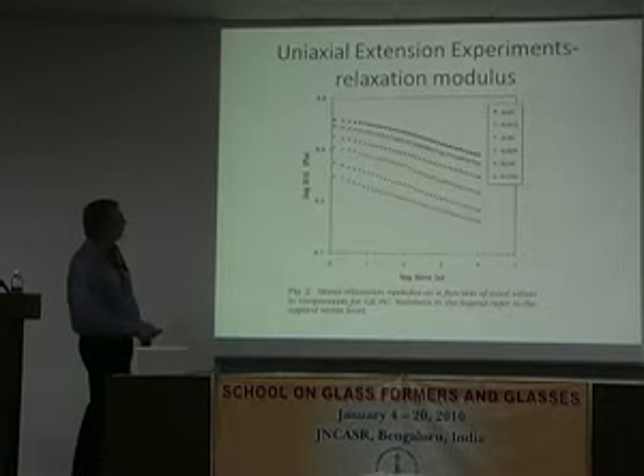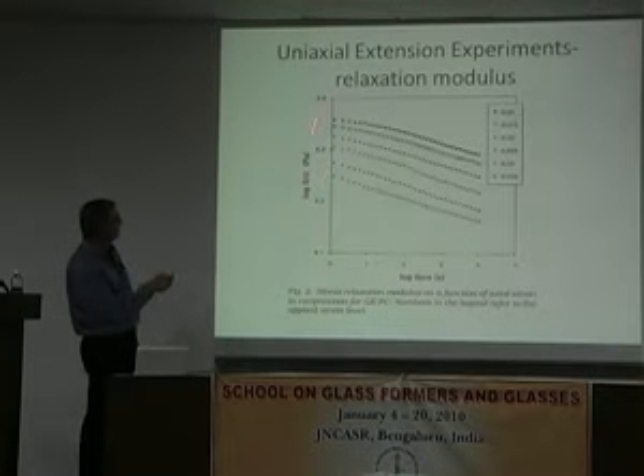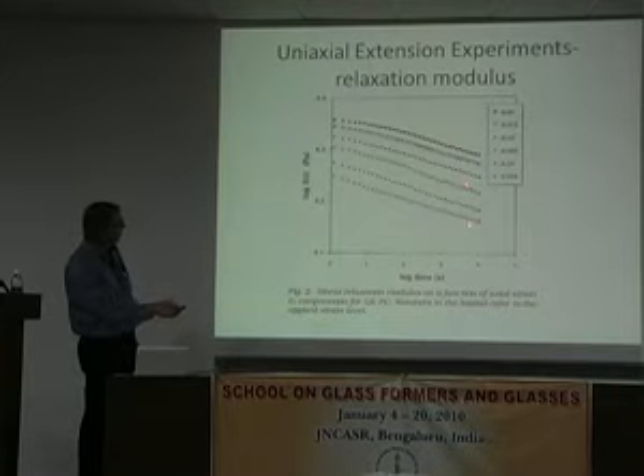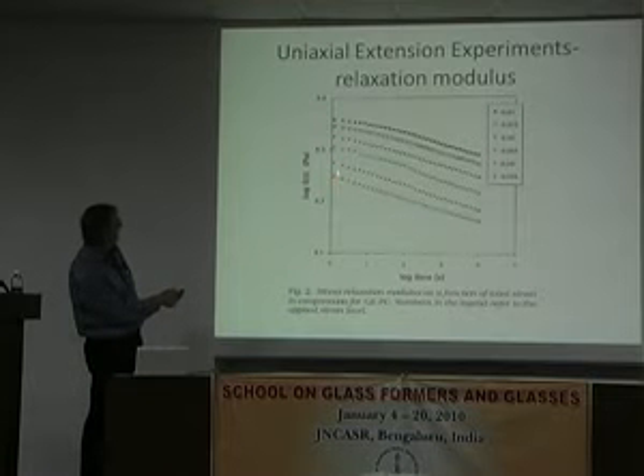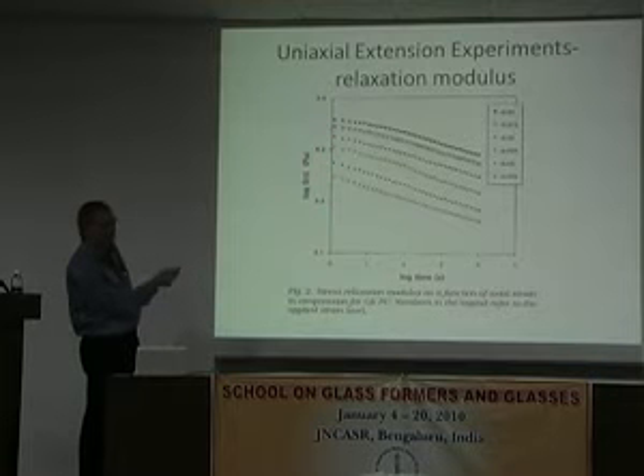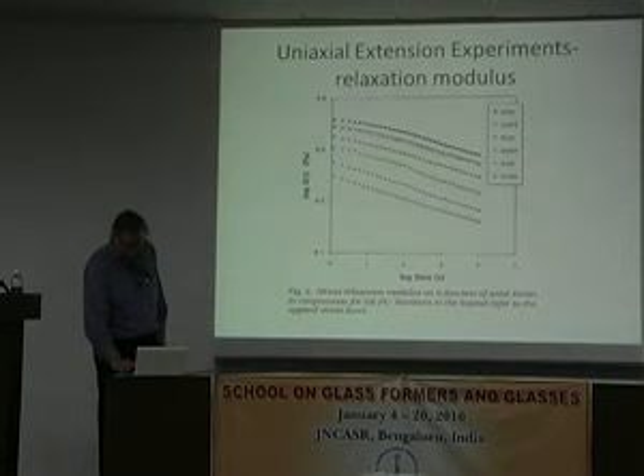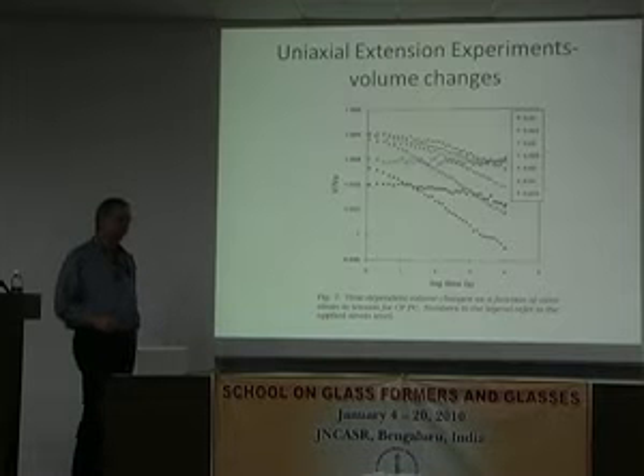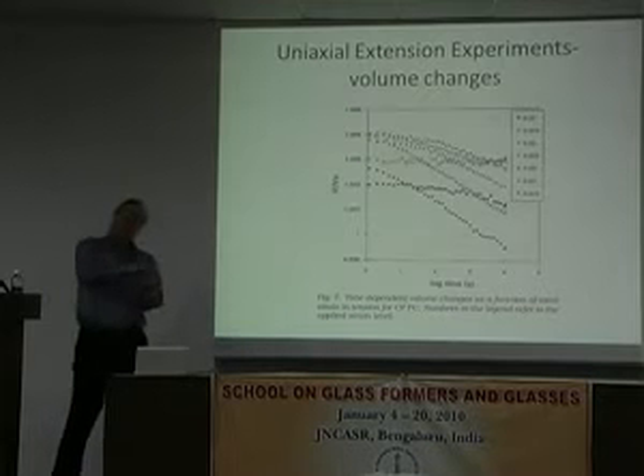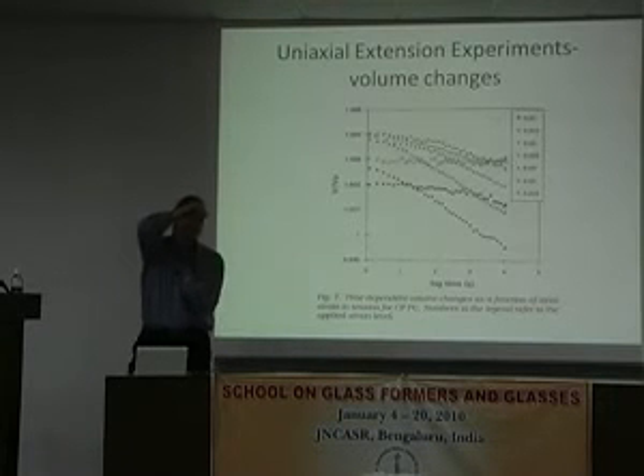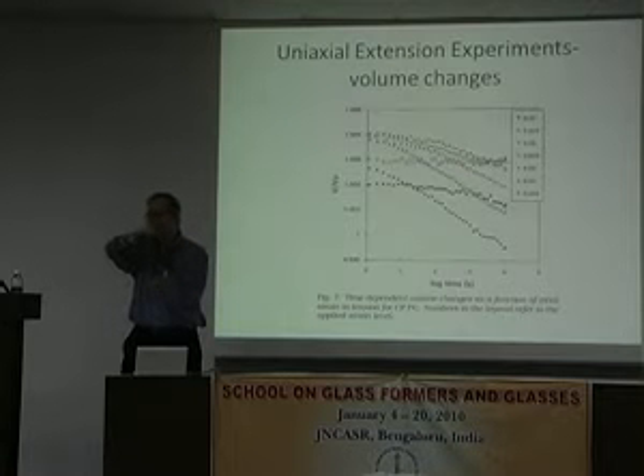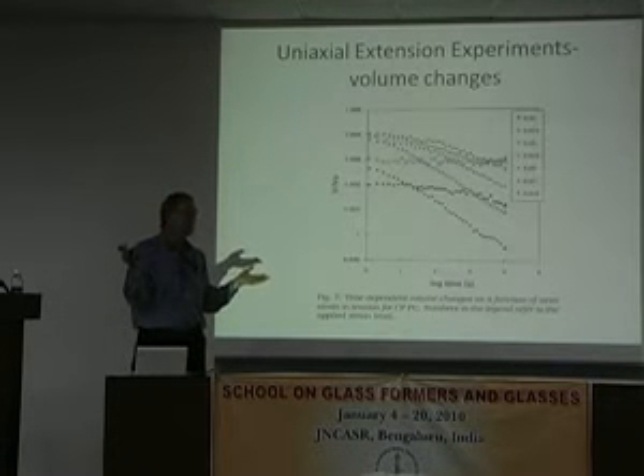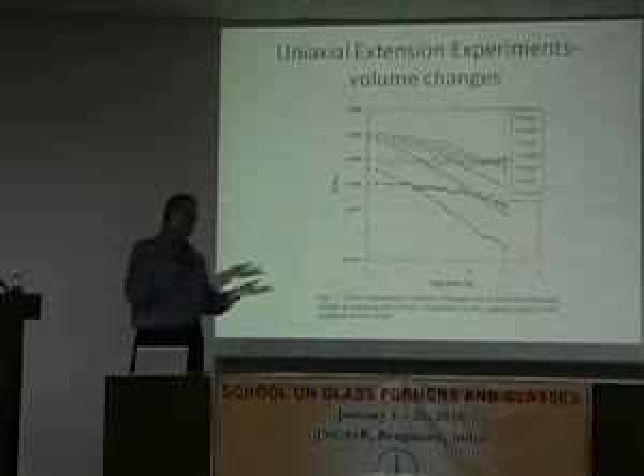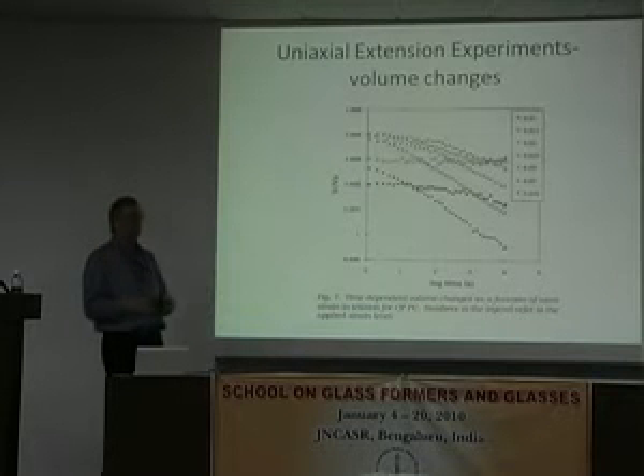And this just shows the modulus. Oh, this is what I was showing you. Here's the modulus as a function of strain. So you can see the modulus goes down as I increase the strain. It's not so much, but it comes down. And we simultaneously measured the volume change. So when you put a viscoelastic material under a deformation, all the properties are time dependent. The Poisson's ratio, the bulk modulus, the shear modulus, the extensional modulus, everything's time dependent or frequency dependent.